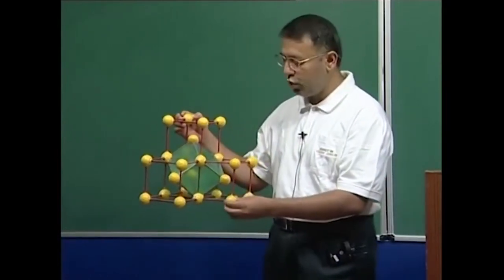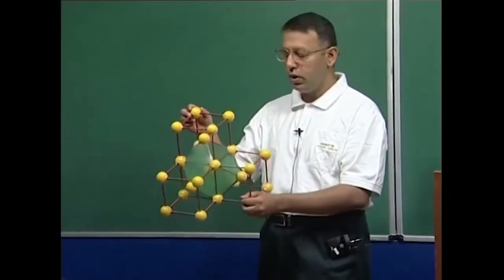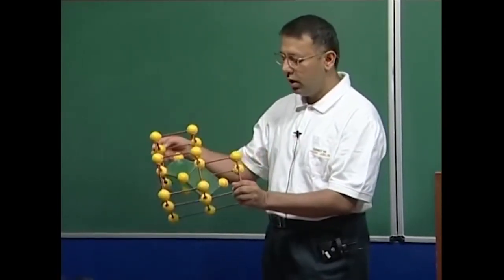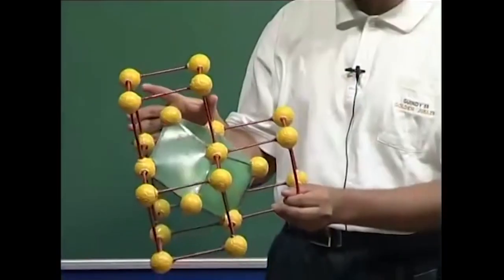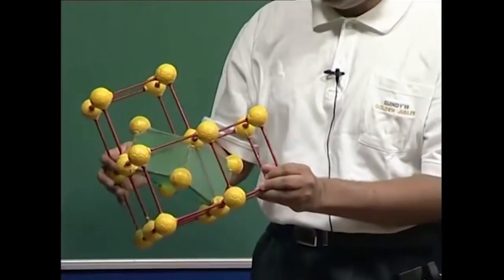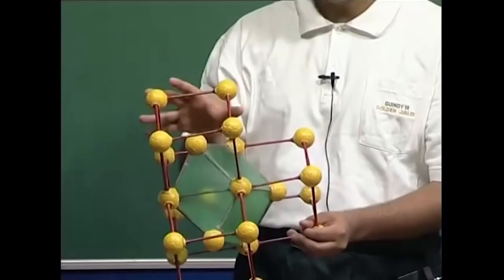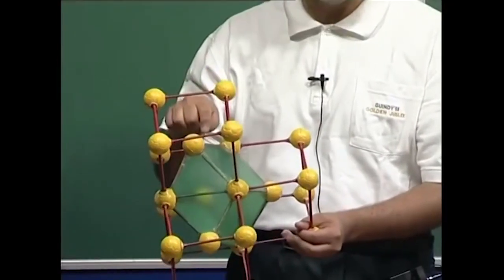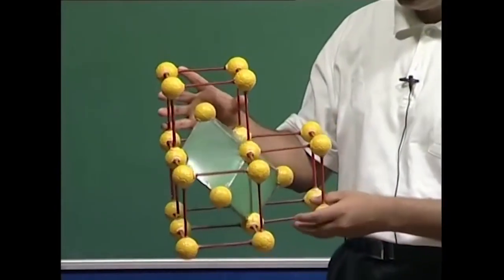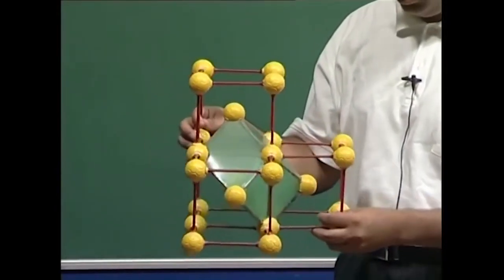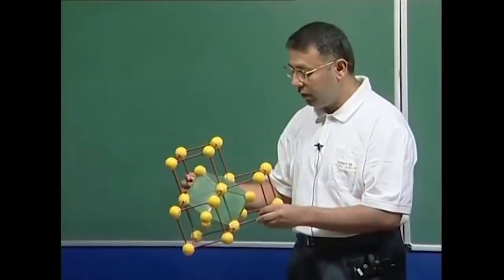This is a rather oblate kind of parallelepiped, but all kinds of parallelepipeds are space filling. So this primitive unit cell will also be a space-filling unit cell which fills entire space. We do not use this as the conventional unit cell — we use the one represented by the red outlines. The volume of this parallelepiped is half the volume of the conventional unit cell, because there is only one atom associated with each primitive unit cell versus two for the conventional one.